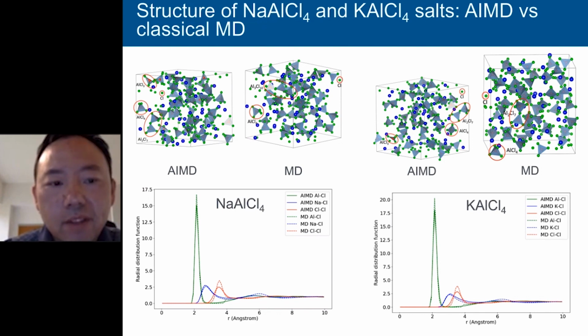Instead, it will form some longer structures, like a trimer, the aluminum 3 chlorine 10 structure. This kind of thing will form in the liquid state. In the AIMD, we only see the smaller, like aluminum 2 chlorine 7 units. So this is actually due to an artifact of the potential itself. If you look at the radial distribution function below, actually the results are decent. Even despite these challenges, the classical MD can reproduce many of the features of the results from the Ab Initio MD simulations.